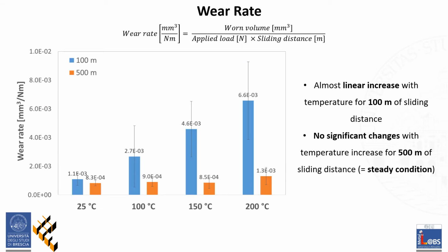Wear rate was calculated for every temperature, both after 100 meters and 500 meters of sliding distance, following the formula above, starting from profilometric measurements that allowed the worn volume determination. Results are reported in the graph. For each temperature, wear rate is higher in the first 100 meters because of greater material removal, as can be seen from the blue histograms. Moreover, a greater standard deviation can be noted in these cases, due to larger variation of the track width in the initial part of the test.